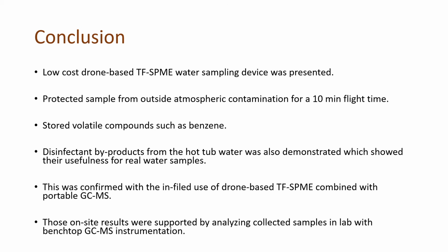In conclusion, we presented a low cost drone-based thin film solid phase microextraction water sampling device, and it protected the sample from outside atmospheric contamination for at least 10 minutes of flight time. It also stored volatile compounds such as benzene, and it determined disinfectant byproducts from the hot tub, which shows its usefulness for real water samples. This was also confirmed with in-field use of the drone-based thin film solid phase microextraction combined with the portable GC-MS, and those on-site results were verified by analyzing the collected samples in the lab with the benchtop GC-MS instrumentation. Thank you.